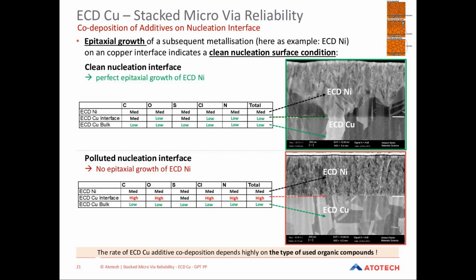At the bottom of the page, with a red highlighted image, you can see now the opposite situation. We have here a different electrolytic copper process. On top of this electrolytic copper surface, we have a lot of adsorbed additives remaining from the copper plating process. So the interface, which is indicated by the red arrow, is highly contaminated, especially with chloride and nitrogen, which are clear indicators for electrolytic copper additives which are remaining here. And the electrolytic nickel process will not start with epitaxial growth in the nucleation.